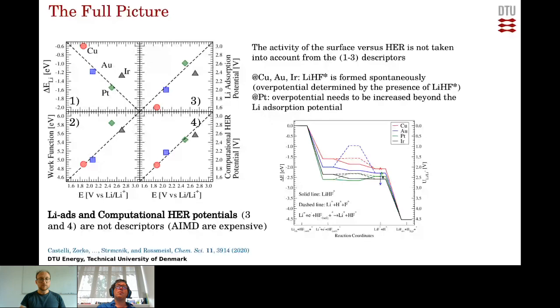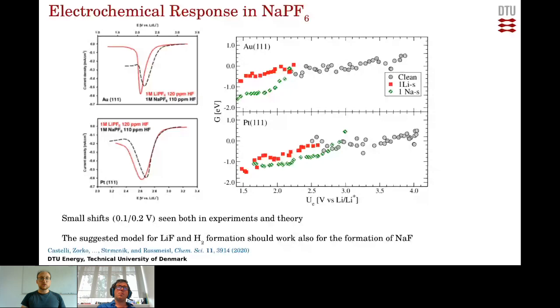We can also try different kinds of electrolyte. Instead of using LiPF6, we use NaPF6, and we can see that there is just a small shift. This has been seen both by experiments and by our calculations. So basically the only effect of sodium instead of lithium is to shift the position where we start having the reaction.